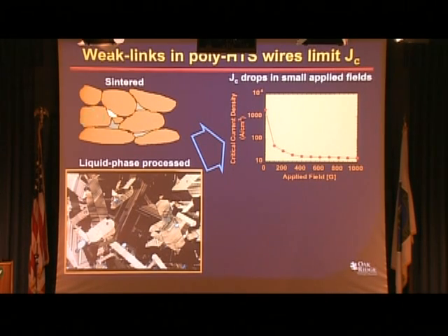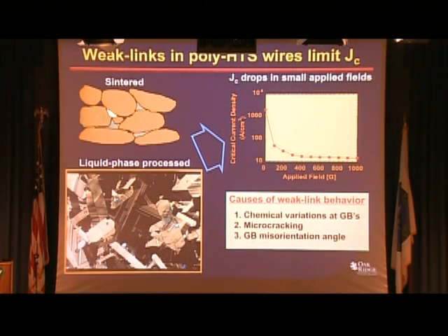And there were many reasons for this. And some of these are listed here. Chemistry at the boundary, microcracking. But the third one, the grain boundary misorientation angle. In other words, how much these grains on either side of an interface were misoriented with respect to one another had a big effect. What do I mean by that?